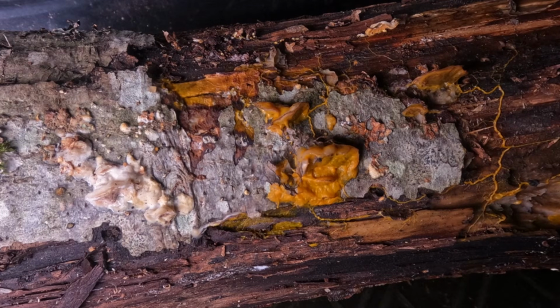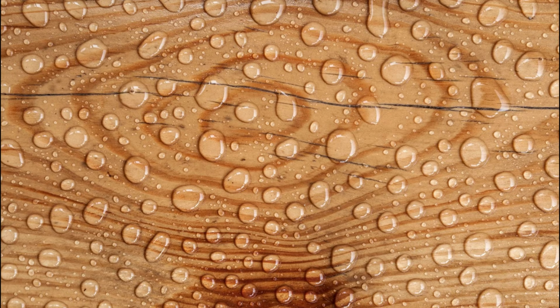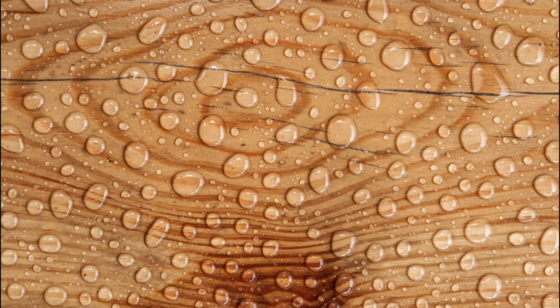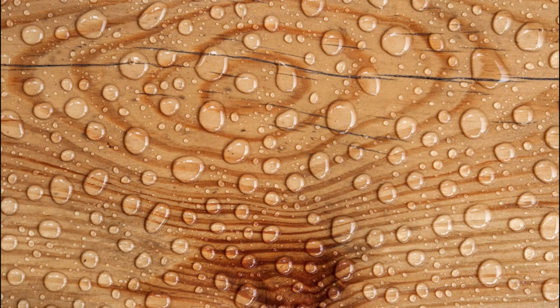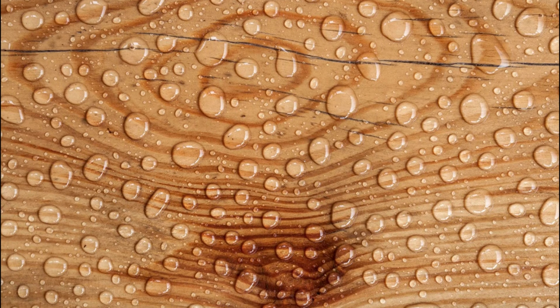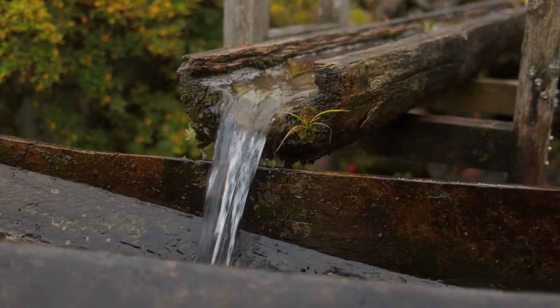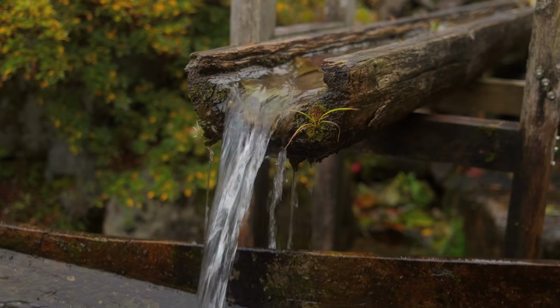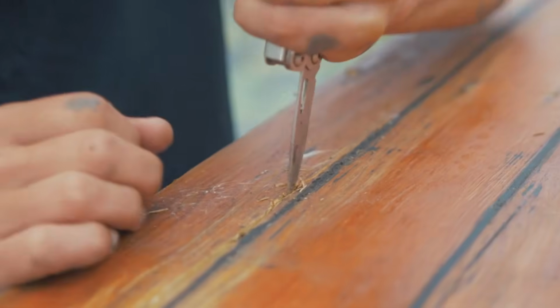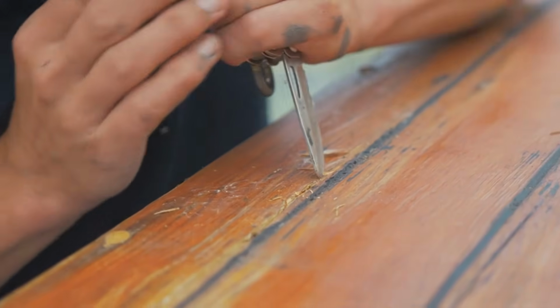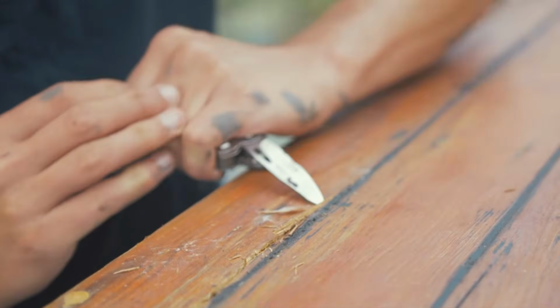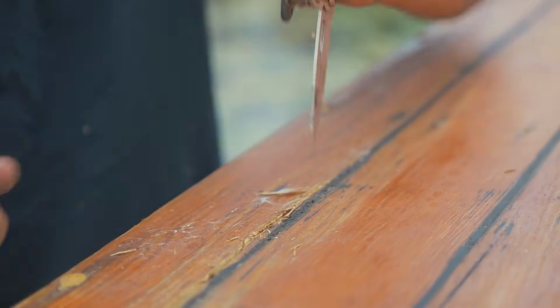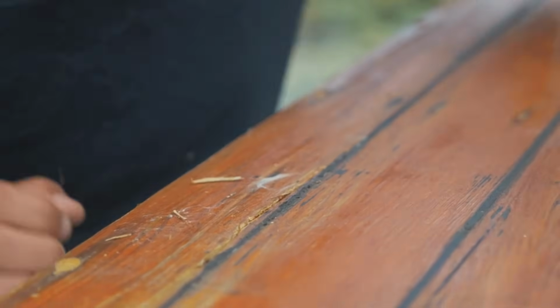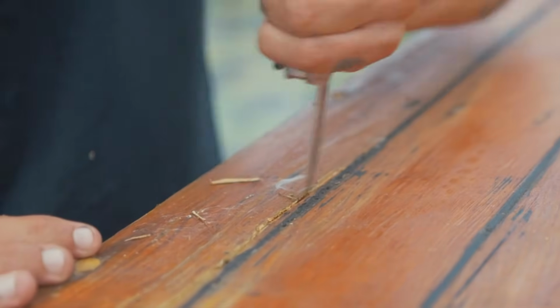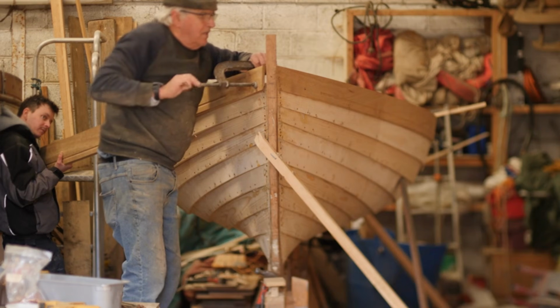Here's the critical rule every shipwright knew. Elm must stay wet. The moment you let it go through a dry and re-wet cycle, it rots faster than almost any other species. That's why it works for keels and underwater pipe, but would be a terrible choice for a deck plank or anything above the waterline. The old builders understood this perfectly. Elm below the water, oak above it. Right species, right location.